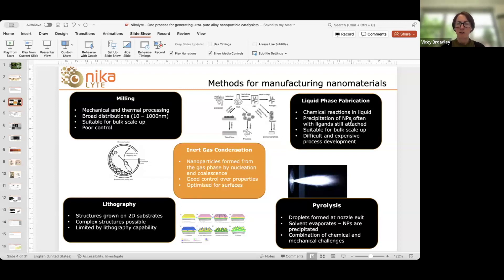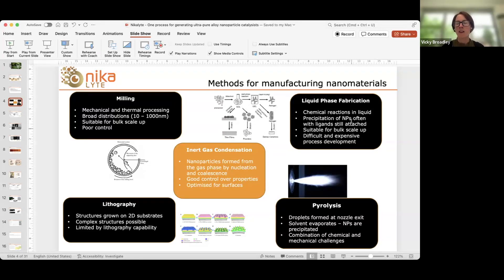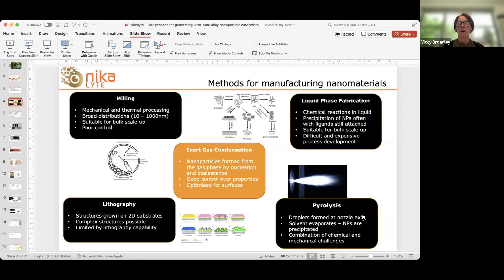For catalysis, where size is really important and we're looking at the smaller end of the range of 10 to 1000 nanometers, milling is not really suitable. Lithography is another technique, not so much in catalysis, but in other application areas such as surface-enhanced Raman and photonics. Lithography is used to generate 2D structures and nanostructures on surfaces and affords great control and repeatability, but it's complex and expensive, so it tends not to be used for scale-up processes such as catalyst generation.